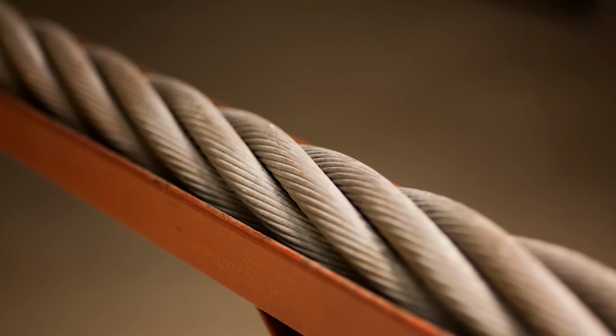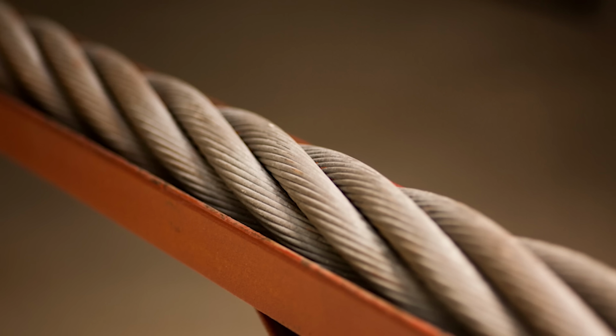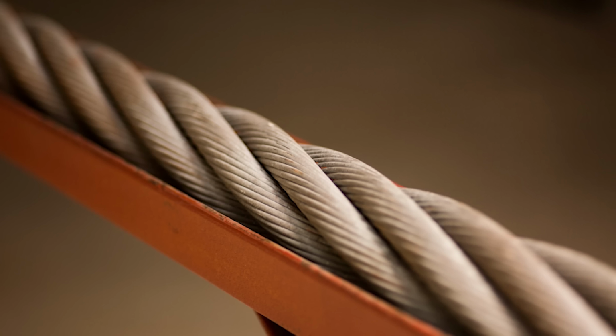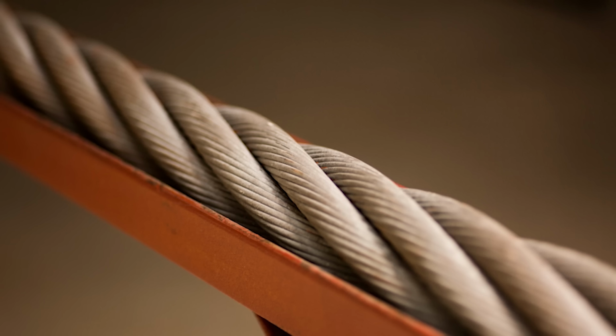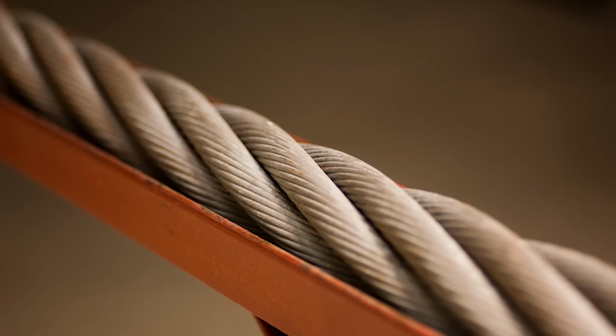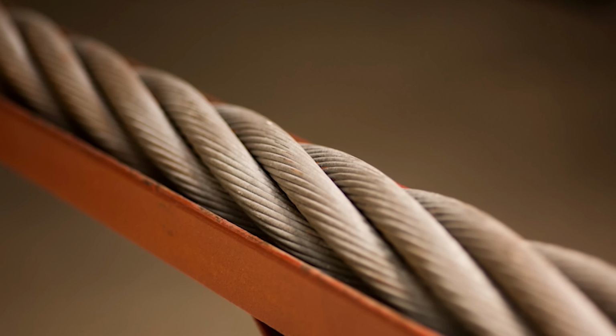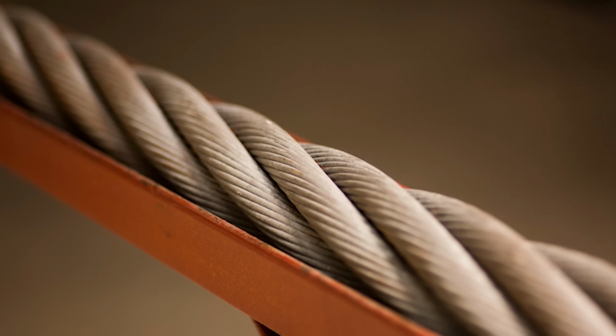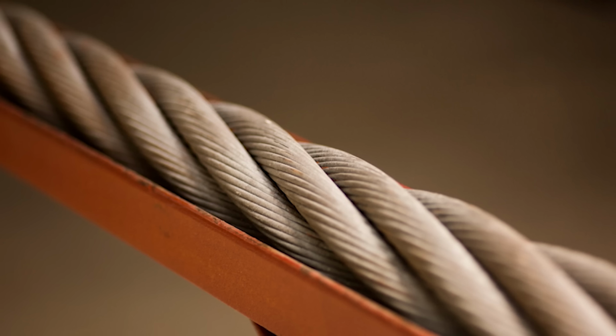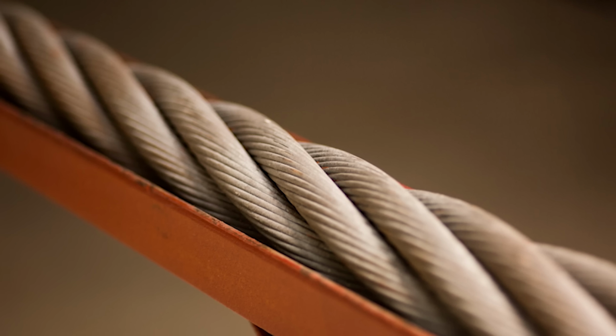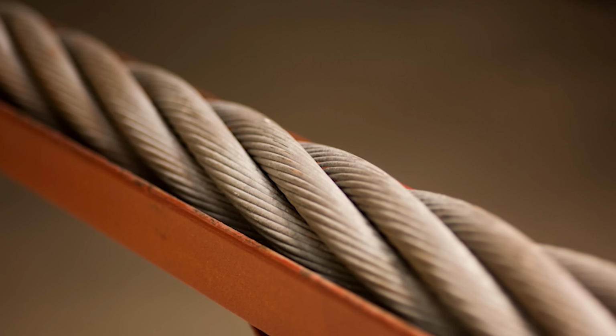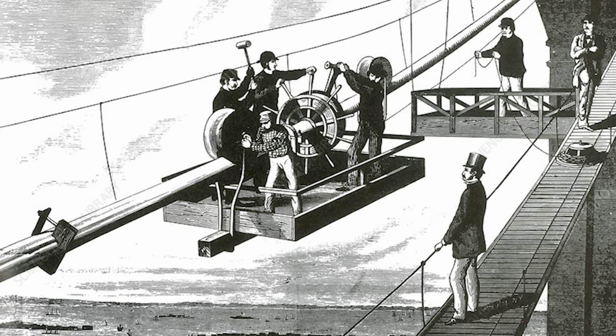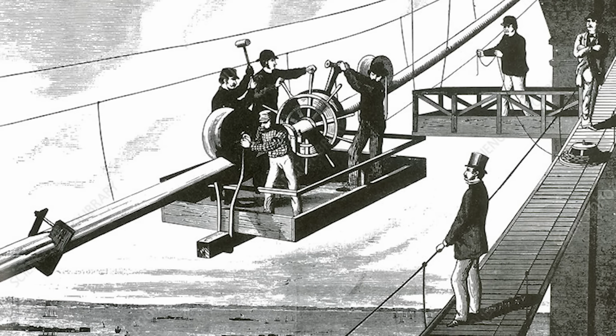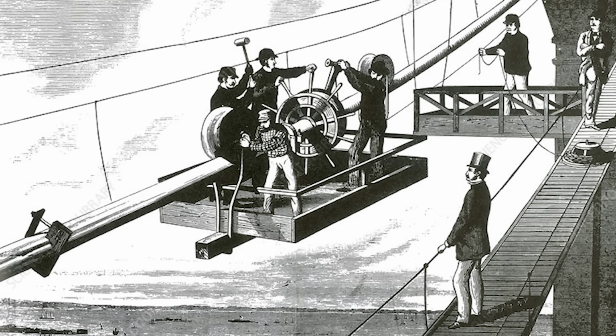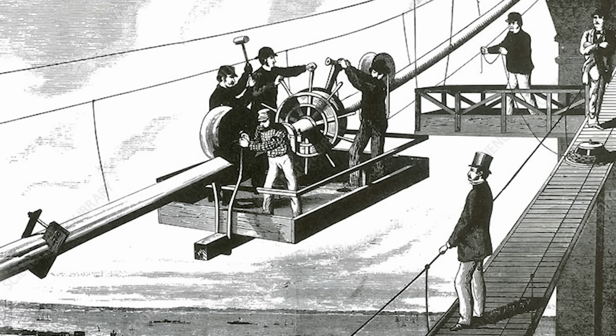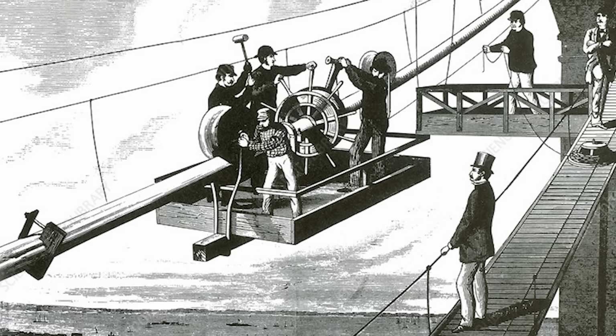The wire specification called for tensile strength approaching 160,000 pounds per square inch, but strength meant nothing if corrosion reduced the effective cross-section year by year. The zinc coating, measured at approximately 1 ounce per square foot minimum, would provide the time that strength alone could not guarantee. If the zinc failed, the bridge failed. Not immediately, steel possessed remarkable strength even when surface corrosion began, but inevitably. The mathematics of deterioration were as predictable as the mathematics of load distribution.